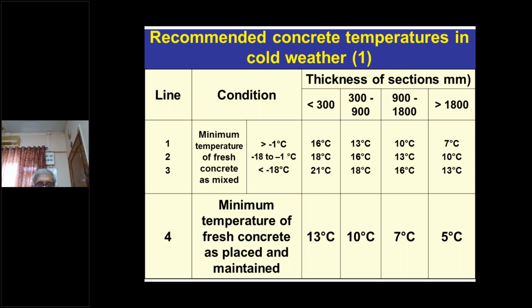Recommended temperatures are given in this chart for different weather conditions. More than minus 1 degree, between minus 18 and minus 1 degree, and less than minus 18 degrees. The thickness again plays a very important role in concreting in cold weather also, just as in hot weather. And you can see at minus 1 degree centigrade, the temperatures can be 16 degrees of concrete and 7 degrees if the massive pour is there. But I can tell you at minus 1 degree to get 16 degrees centigrade concrete temperature is extremely difficult. Manageable is about, say, 7 to 10 degrees centigrade.